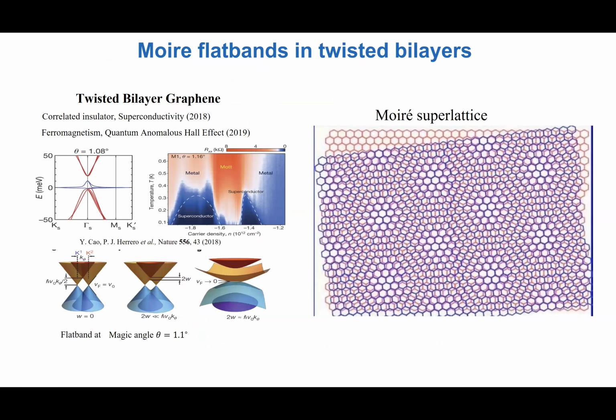That is, instead of putting two materials that are identical right on top of each other, if one introduces a finite angle, then the stacking of the atoms in the two different layers has a periodic modulation, in the sense that at this side, for example, you have two atoms of the same kind sitting on top of each other, and that configuration is reproduced at a certain distance, which is the Moire length scale. And how far away these scales are is determined by the twist angle. Okay, so that's how one can understand the formation of this new superlattice, which can be very uniform, and not always, but can be, and gives you this new periodic landscape that could allow you to modify your band structure. Okay? So that's the idea.